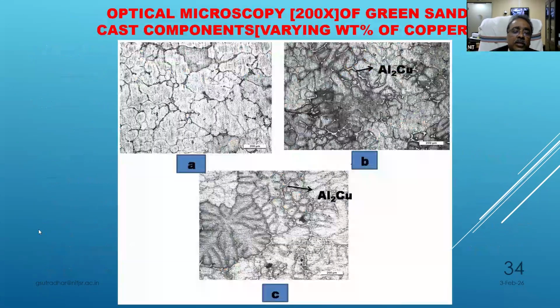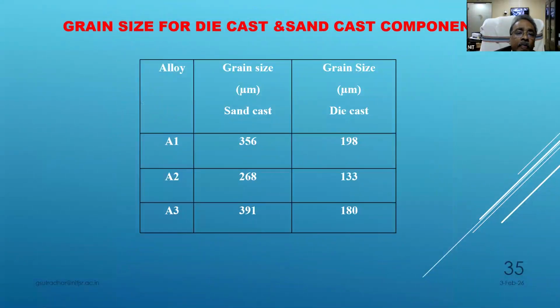If you see this structure, this is an optical micrograph of green sand cast components before heat treatment. This is for 4% copper with the same magnification. This is Al2Cu, still more, and this is for 12%, where the grain boundaries are very visible to the naked eye at 200x magnification. The Al2Cu amount is going up, and this is basically increasing the hardness. So this is for die casting and sand casting composition.